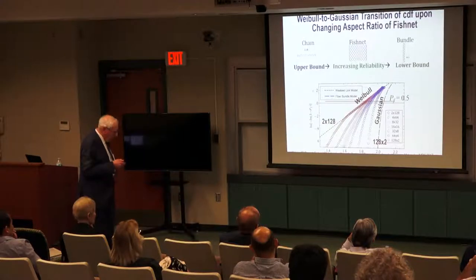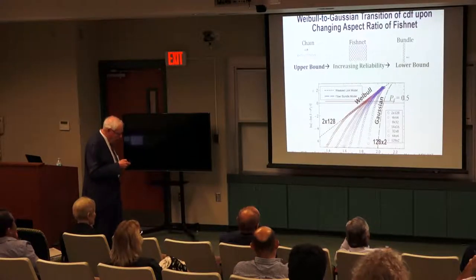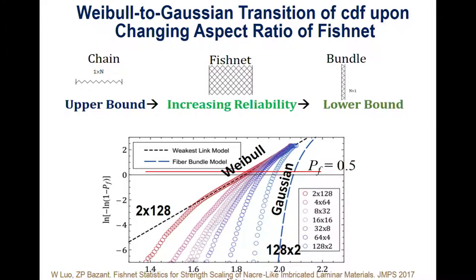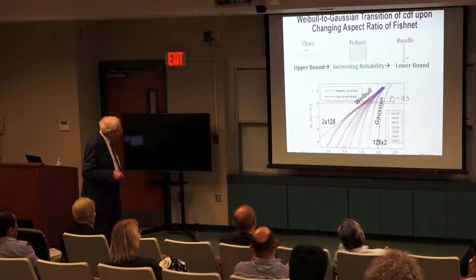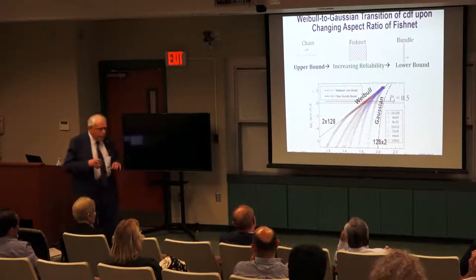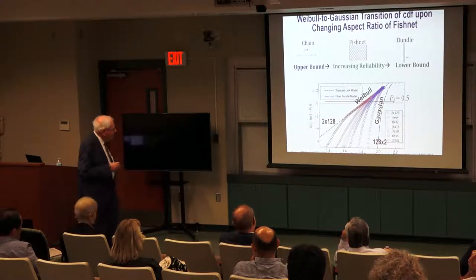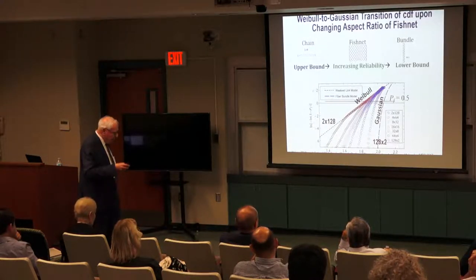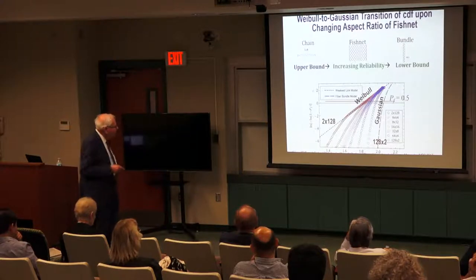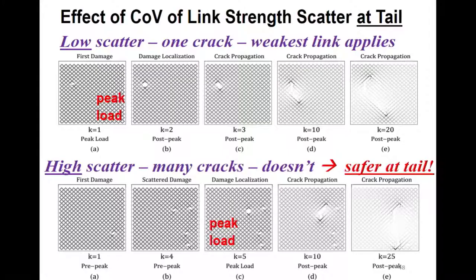Now, this was done very carefully computationally by Lo. Each point is 10,000 simulations, and here we move from 2 times 128 to 128 times 2, from chain to bundle, and you see this continuous transition. It is not a superposition of these two simulations, it's very different actually. If you tried to put a partition of unity combination of these two distributions, it would be incorrect, it would be very different. Now, interesting is the role of scatter, which is very interesting.